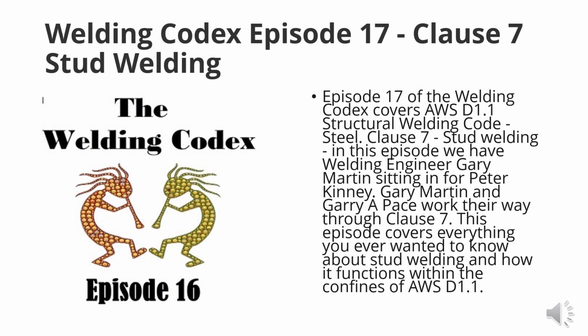All right, so this would be normally where 7.5.5 is. It's added two numbers in the 2020 code, the 9.5.5 fillet welding option. At the option of the contractor, studs may be attached with fillet welds using a WPS qualified in accordance with Clauses 5 and 6. We went over that. And then it has two subclauses: production control, conformance to 9.7, which would be 7.7 in the 2015 edition, shall not be required for studs attached by fillet welding.